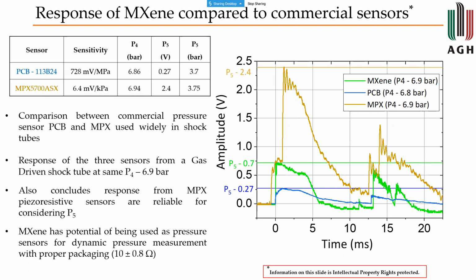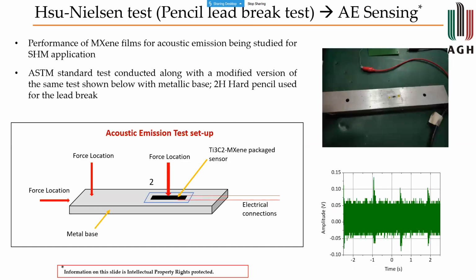And going further, we did perform a standard lead break test, which is used to measure the acoustic emission event in a metallic sample. This can also be done with an acrylic rod, which is quite standardized, and an ASTM test specification exists for them. But we did try it with a metallic substance so that we could have some experiments close to reality that we do in our lab.